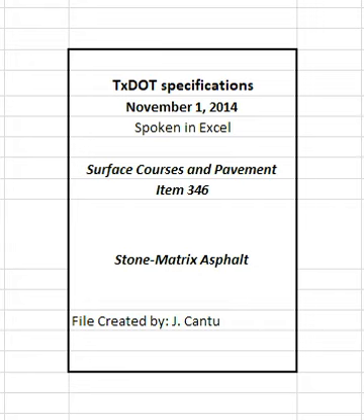Perform a density profile every time the paver stops for more than 60 seconds on areas that are identified by either the contractor or the engineer as having thermal segregation and on any visibly segregated areas unless otherwise approved. Perform a minimum of one profile per sublot if the paver does not stop for more than 60 seconds and there are no visibly segregated areas or areas that are identified as having thermal segregation.